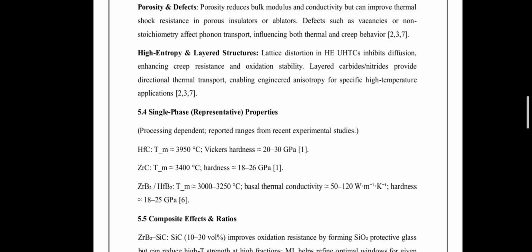There is a reported range. Melting point for hafnium carbide is 3950 degrees and their hardness is 20 to 30 GPa. Melting point for zirconium carbide is 3400 and the hardness is 18 to 26 GPa. While for the borides, their melting point is 3000 to 3250 degrees Celsius. Their thermal conductivity ranges from 50 to 120 and hardness 18 to 25 GPa.